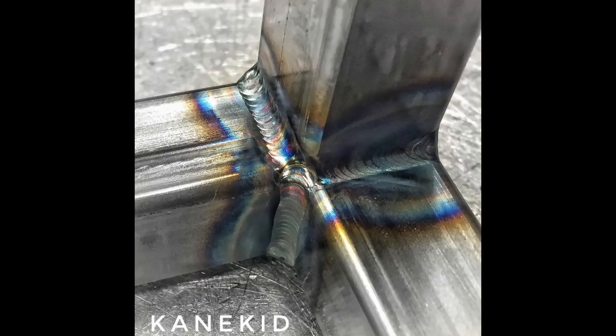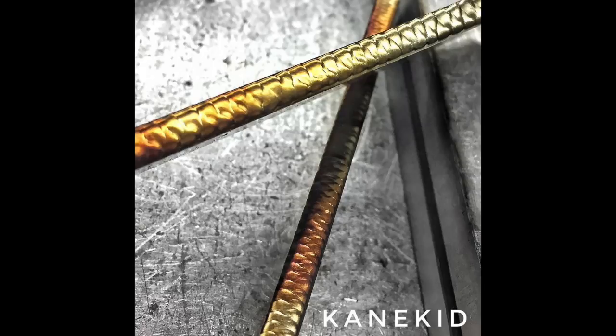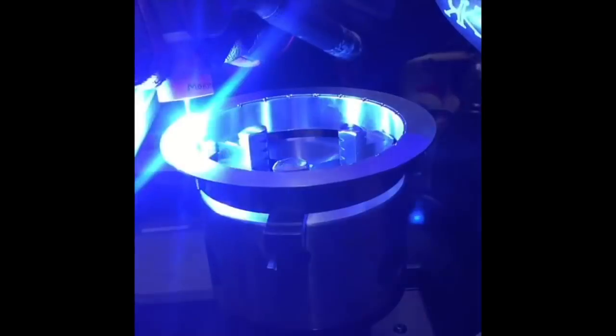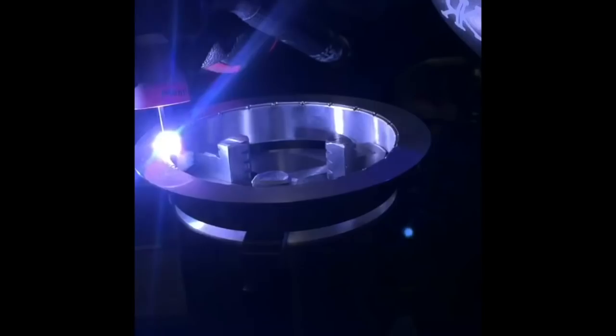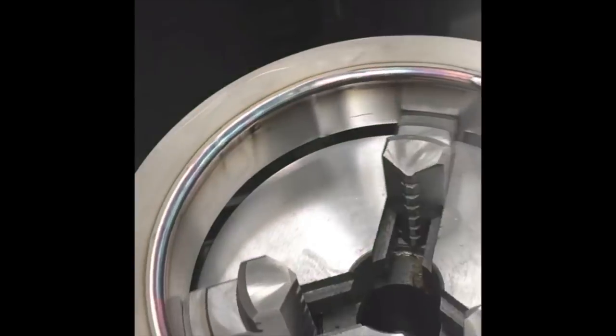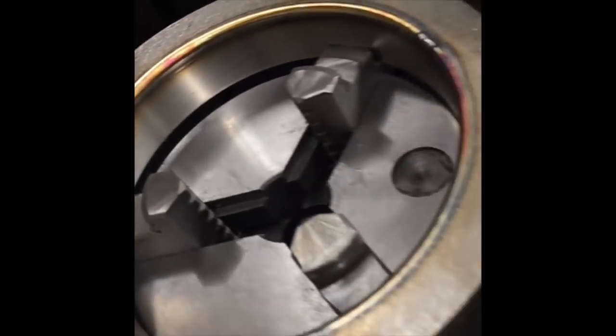It was at like .035 wall, and some of it even a lot thinner. But on the little thin wall tubes, those are all purge welded too. That's a struggle in itself. Getting the flows right, getting the right CFH on the inside of the tube and the right CFH coming from the torch. To purge the insides of a tube with that thin of wall thickness, I'm running about 2.5 CFH on the inside and about 7 to 10 on my torch.